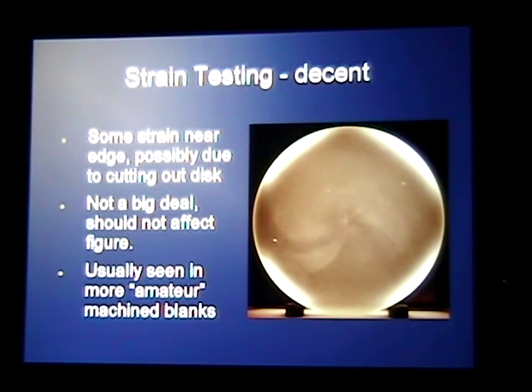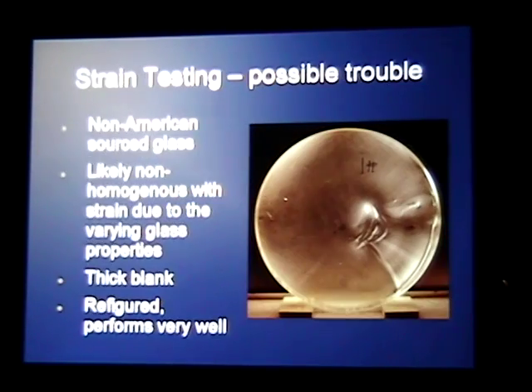Here's a decent strain test. Now you see we start to have these light areas out here, and we have this four-sided symmetry. This region is almost a diamond or a square shape, and this is pretty typical of strained glass. You see these two axes of strain, and since the polarizers are rotated 90 degrees, some of that has to do with how the test is set up. So in this case, this is not bad. This made a fine mirror, and I didn't worry about the strain too much. But we'll show some worse ones here.